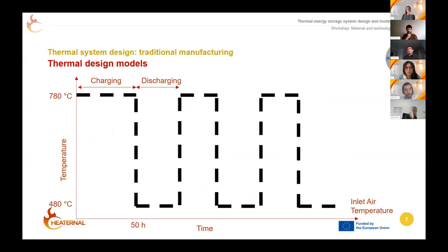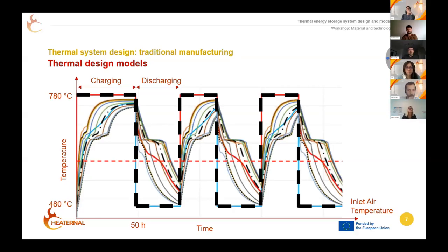Now, if we go to our traditional manufacturing, you need to make a thermal design model. And then you need to put inputs and outputs to the system. And how does this look like? This looks like this. You have a temperature on one axis, the y-axis, and time on the bottom. And you apply a cycle of charging and discharging where you have an air inlet. And we've defined it constant now for a certain amount of time. And you apply this to a thermal model. And from that thermal model, you get the temperatures of the outgoing air, but also temperature inside your systems of PCMs and refractory. And you want as much energy stored, of course, as possible, and thus as high possible temperature difference between your in and your outgoing air.